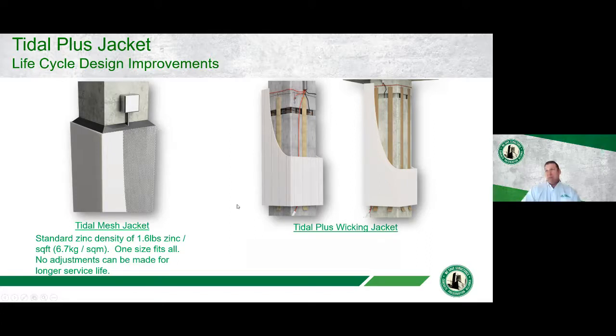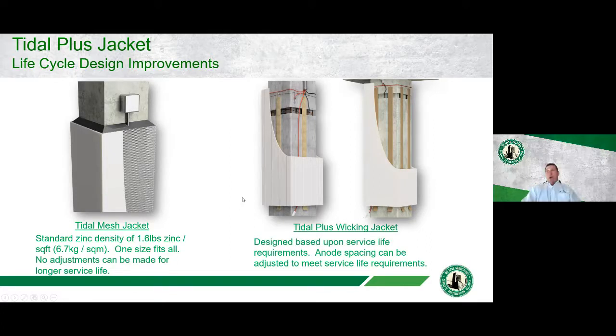With the Tidal Plus, having them made with discrete anodes, we have the ability to increase the amount of zinc within the cathodic protection jacket. In this first example, we have four anodes, one to each face. In the second, we have essentially doubled the amount of zinc on this pile with two anodes per face. Increasing the amount of zinc obviously increases the volume, so it increases the life cycle or the design life of a cathodic protection jacket.